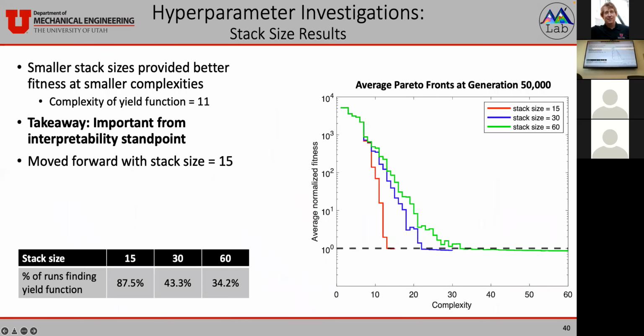Moving on to the stack size. What we saw is that smaller stack sizes performed better than larger stack sizes. I'm showing that through Pareto fronts, which we discussed earlier. Stack size of 15, which is denoted with the red line, has better fitness at smaller complexities than larger stack sizes. This is important from an interpretability standpoint in practice. You're often wanting equations with small complexity and with good fitness. And so stack size of 15 was able to do that best.